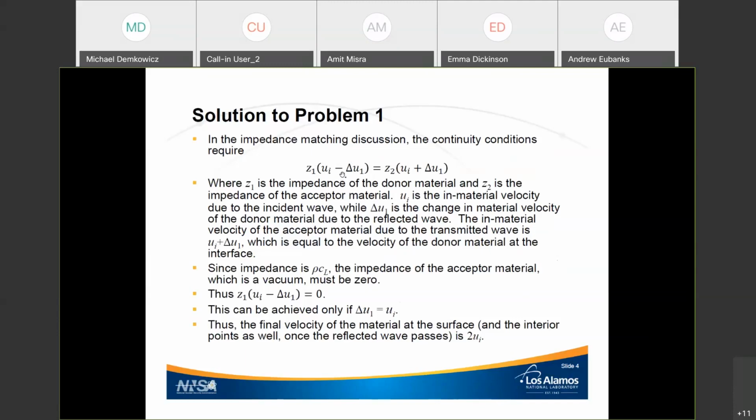So in this case, effectively, when a wave is reflected into the material, if the wave that is reflected is also a compression wave, then that actually slows the material down in the laboratory reference frame. If it's a tension wave, then it actually speeds the material up. But fundamentally, this is the equation that we have to satisfy. Okay, well, the impedance, of course, is the sound speed or the wave speed times the density. So rho times C_L for a longitudinal wave.